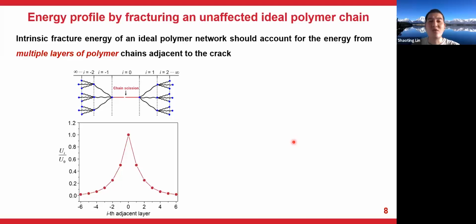Let me start with an ideal polymer network. An ideal polymer network means a polymer network has a uniform chain length, a uniform functionality, and is free of defects. And once a crack propagates, it will first relax the energy stored in the fractured polymer chains. And for the neighboring chains at adjacent layers, although they are not fractured, their elastic deformation still provides the relaxed energy as an additional energetic contribution to drive the crack propagation. So here we calculated the energy stored at the different layers. And as we show here, the relaxed energy is delocalized over multiple layers.